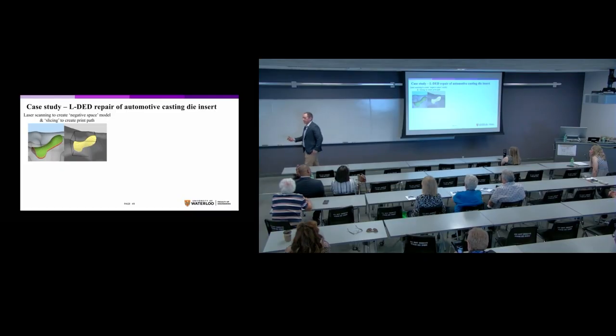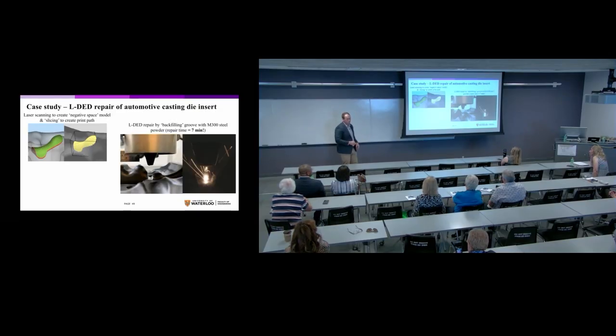And so then we took this negative space model and we put it into our printing software and we created a print file here. So that's that yellow bit there. So essentially, it took this void in our part and we created a printable part. So we've segmented here and we created the tool path. And then all we did after that, we took the part, we put it into the printer, we lined everything up, and we essentially just hit print. It's of course not as simple as that, but we just hit print.